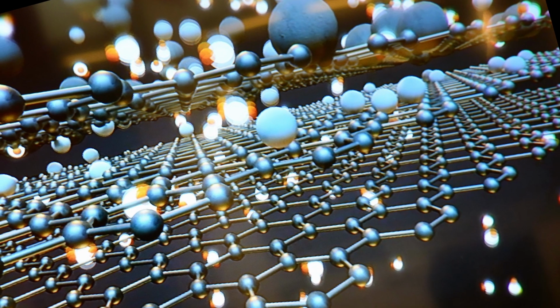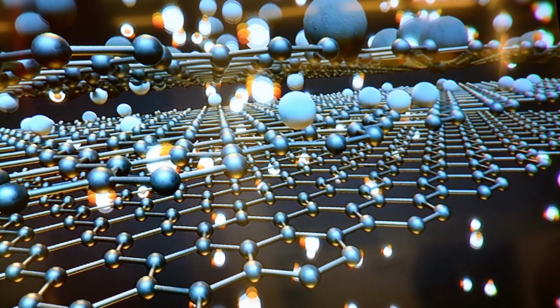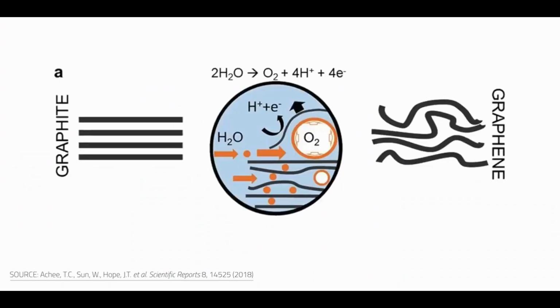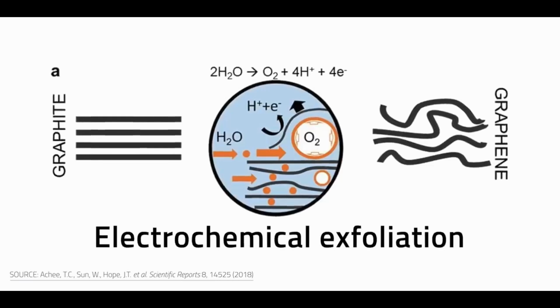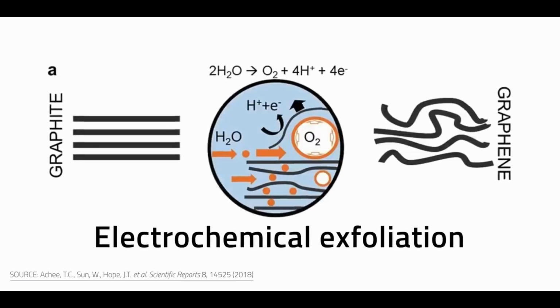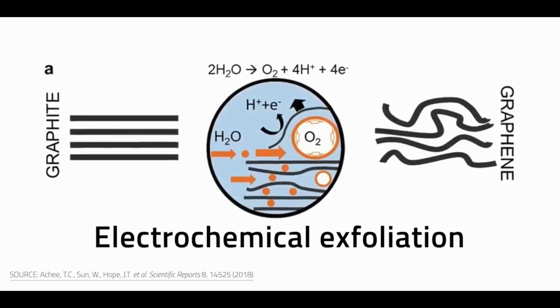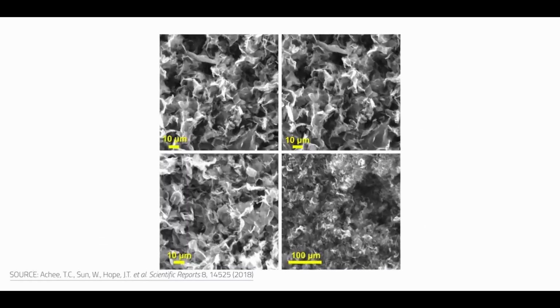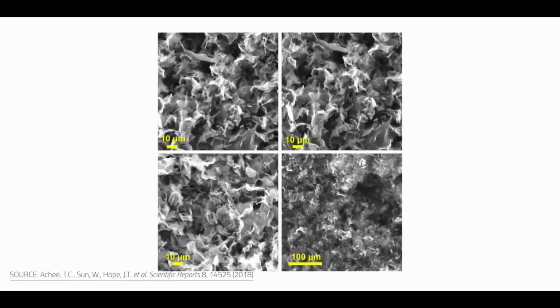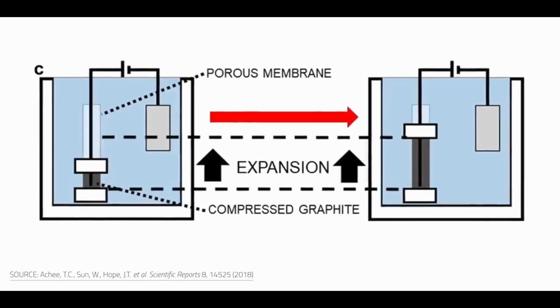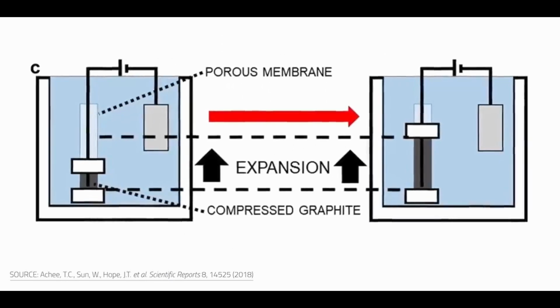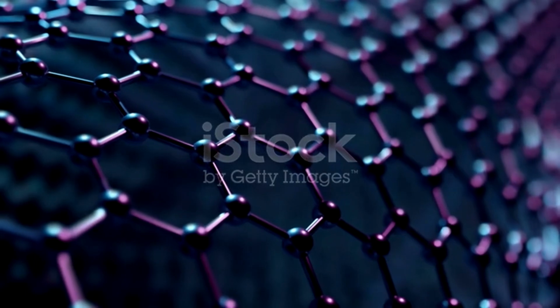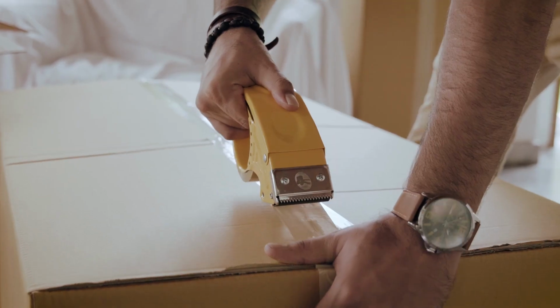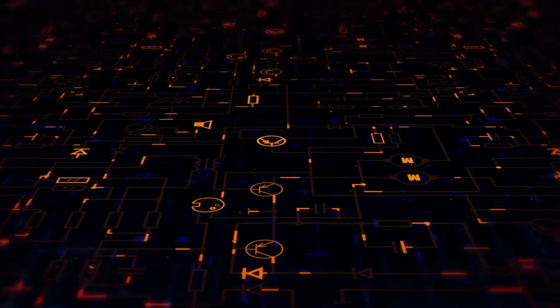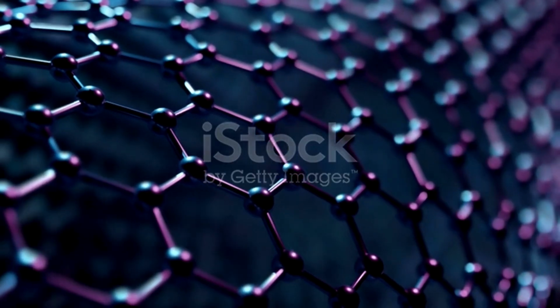Graphene reduces the surface energy forces that cause agglomeration, or clumping, of the newly fractured cement particles. To do this, they produce graphene based on electrochemical exfoliation, in which graphene is obtained from graphite when a voltage is applied to it. The voltage makes ionic species intercalate, basically to inject themselves into the carbon layers where they produce gases that expand and exfoliate individual graphene sheets. Instead of using tape to rip off layers of graphene, you're using electricity to shed off layers of graphene. It basically sheds layers of graphene one at a time.